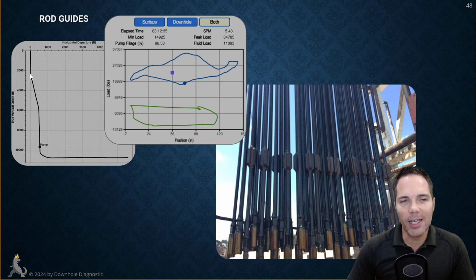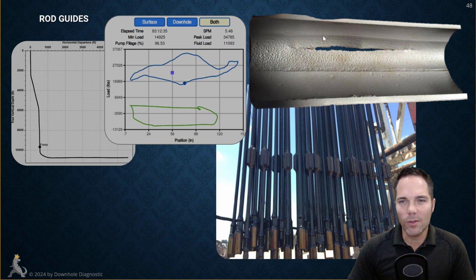If you have lots of deviation like this, you might get cards that look like this, and we'll talk about this. This is a card that indicates shallow friction, meaning that there's some friction higher up on the rod string that's not properly being accounted for with the one-dimensional wave equation. The indication that it's not properly being accounted for is the distorted shape of the downhole card. You can see the shallow friction effects in these slants occurring right here. Also, there's some distortion. That's not how a pump card should look, but this can happen when we have a lot of these deviated wells. And of course, this is going to lead to accelerated failures.